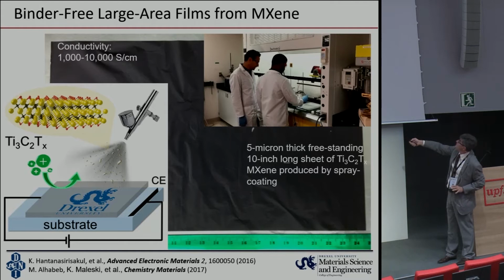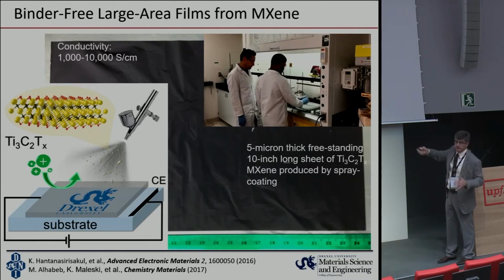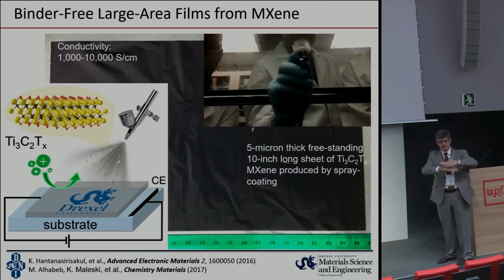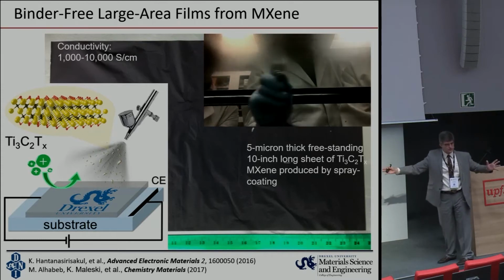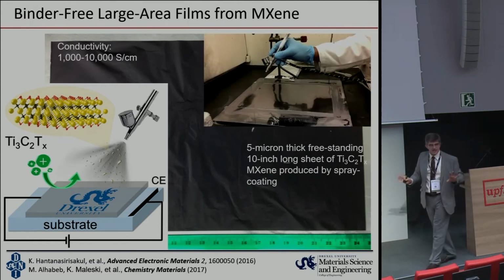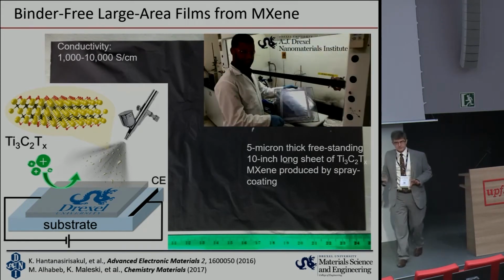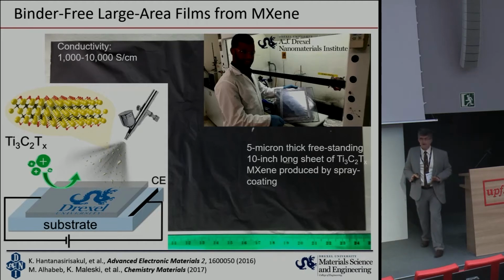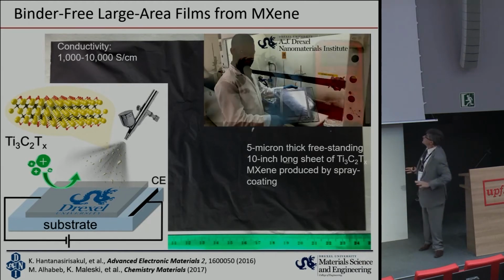Depending on how flakes are aligned, you will get lower or higher conductivity, denser, better aligned film. Larger flakes naturally give you higher values here. And these values are really, really high. They are higher than any solution processable material I've seen so far. And again, we are very far from the limit.